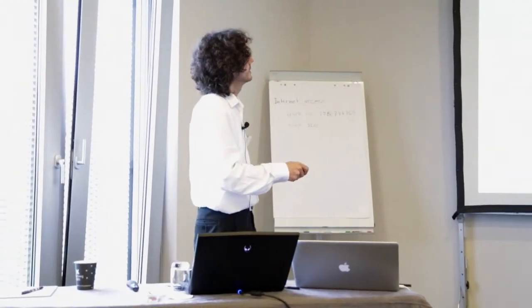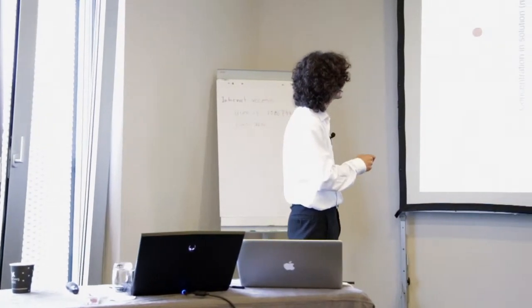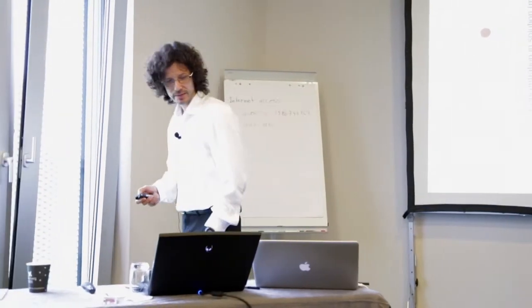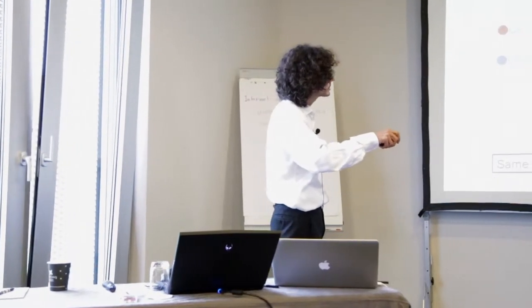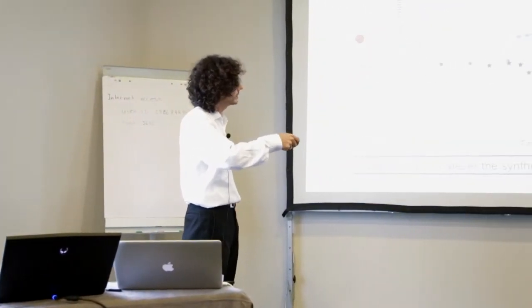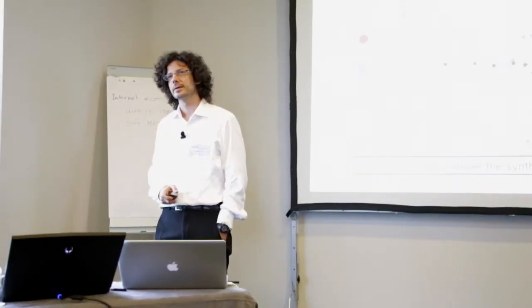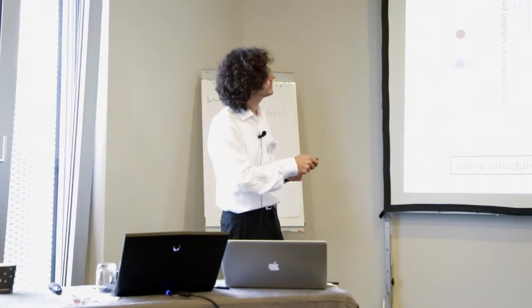The next plot shows something similar for calcium, starting a bit higher, also going through a maximum and decreasing at exactly the same time. If you look at the organic compound in the solution, it is constant over time. You've added it in the solution and it's remaining there, and then eventually it goes down also. So I find this a fantastically beautiful plot, because it's indicating that you have a process of dissolution of the phase. You reach a certain critical supersaturation where you have nucleation, and once you've passed this nucleation point, you get the growth, and this growth consumes the aluminum, calcium, and polymer to form this new phase.